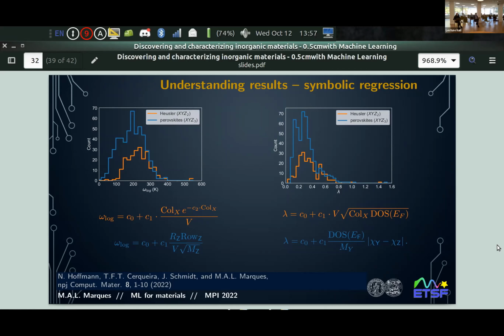And you can see, for example, that lambda is essentially proportional to the square root of the density of states, here the density of states. You see that here, for example, the mass of the Y atoms, of X, Y, Z, is preponderant, much more important than the other two masses, and the difference of electronegativity. So based on these formulas, I can easily understand the behavior of superconductivity in an entire family. Of course, this is an approximation, this is a model, but you can also learn things easily from machine learning, not only predict numbers.